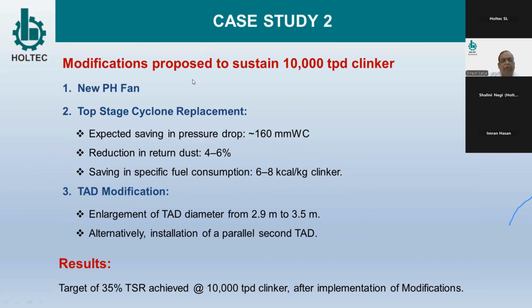Our major proposal was to go for a new preheater fan and the replacement of the top stage cyclone. That also helped in reducing pressure drop and return dust to 4 to 6%, so an overall saving of 6 to 8 kilocalories because of this modification. And then the tertiary air modification, enlargement of tertiary air from 2.9 to 3.5. The idea was that we can even go for a parallel TAD. So the result was that we achieved 35% TSR, and the production loss was averted because we made the required modifications. 35% TSR was achieved.